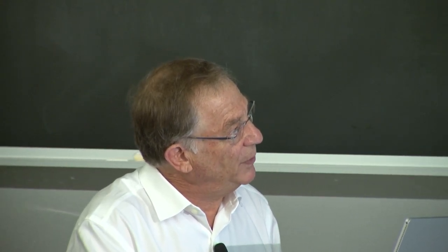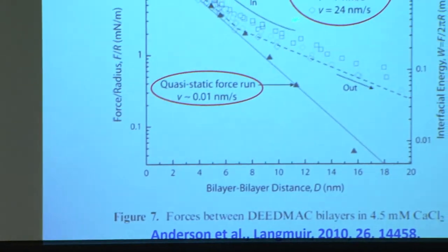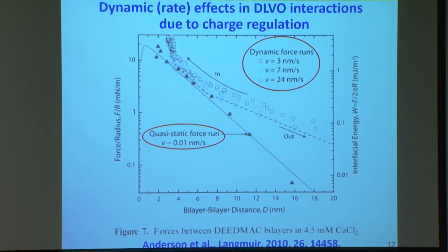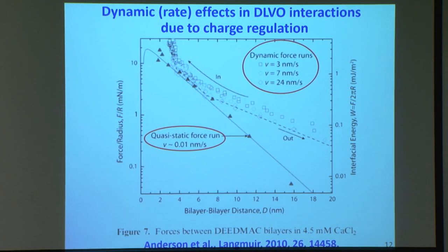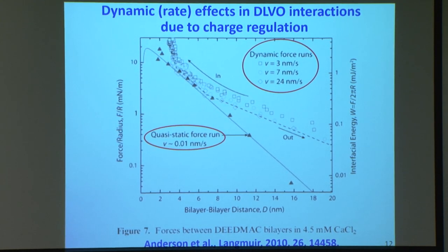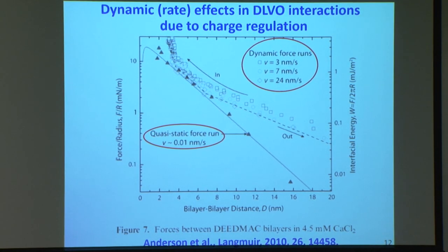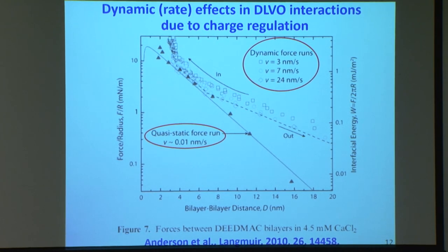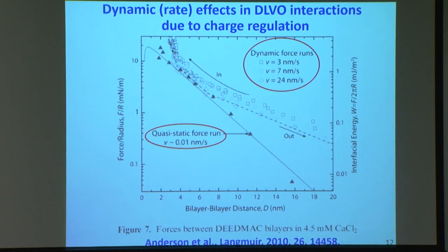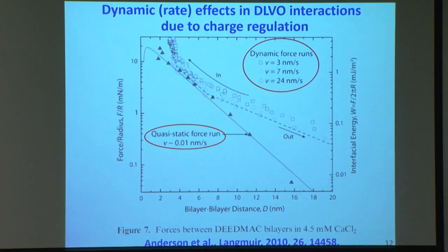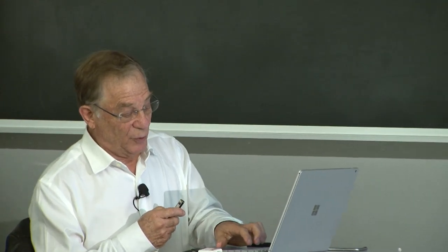What I'm trying to show here is if one measures these forces as a function of rate, even if one goes as slowly as 3 nanometers a second, one totally overestimates the repulsion because the system is behaving more like what's known as a constant charge system. The surface charge hasn't had time to equilibrate with the ions adsorbing on it. You have to go slower than 0.1 angstrom, or 0.01 nanometer, a second to get the equilibrium interaction, where the ions have had time to equilibrate with the surfaces and reduce the surface charge. This is a simple example of how, even at these rates, you are looking at a non-equilibrium interaction where the repulsion is stronger than expected on approach. By the way, usually on separation, it looks more attractive than the equilibrium, but on coming together, it's more repulsive.